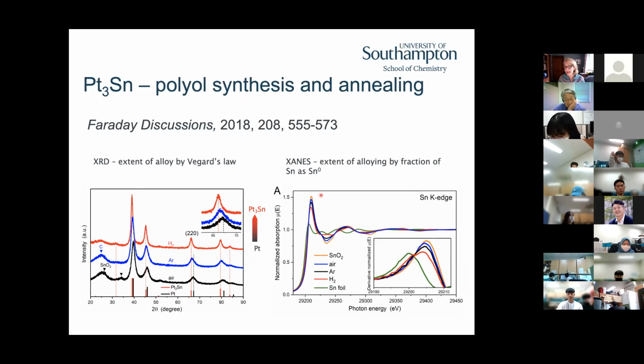If we look at the XANES, let's look at it from this perspective of the tin now. What we can see is that as we anneal, we go from something that really looks like tin oxide, that's the orange. So we're going to anneal in hydrogen. We're bringing this down so that it's looking closer to tin foil. It never gets there, right? But it's moving that way. So we can see that we're changing the oxidation state of the tin.